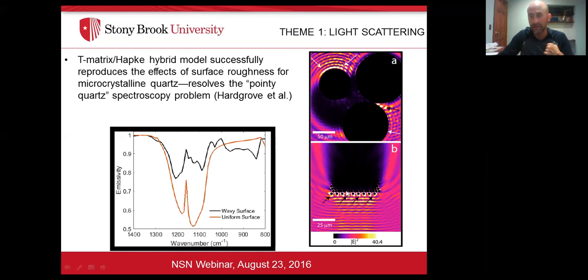Here, you might notice that there are these weird light blobs, and the waves very close to these particles are not symmetric. That's because the particles are about or smaller than the wavelength of light that we're interested in. And here, you're seeing the result of that. When the particles are much larger than the wavelength of light, you get this nice, smooth spectrum. And when the particles are smaller than the wavelength of light, or about the same size, you get this kind